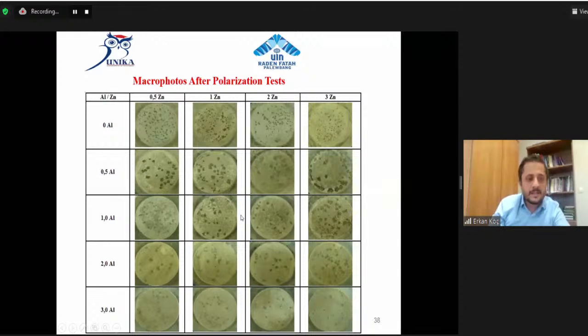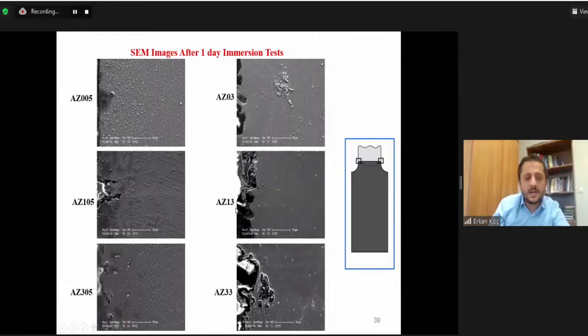And here are some images after 1 day immersion test. As can be understood from the SEM images, corrosion progresses from the surface to the interior. This progress accelerates with the increase of zinc and aluminium amounts. It should be noted that the intensity of aluminium in corrosion progression is much more effective than zinc.